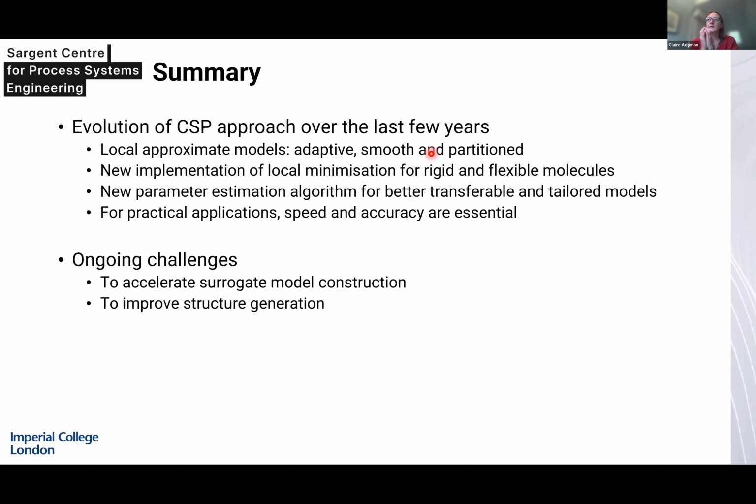They don't influence the intrinsic stability of your crystal structure, but you might see different crystal structures crystallize out of solution depending on the solvent that you have, and then eventually one structure, if it's a metastable structure, will convert to the more stable structure, but that could take years.